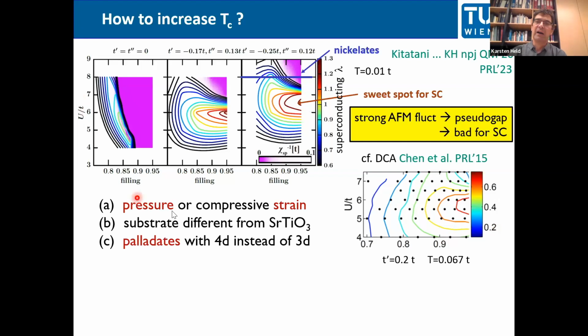And at the very beginning, we proposed 3 different ways to do so. Pressure, or you can also make strain within your plane. And the strain will increase the overlap of the wave functions because the sites are closer together, and that will increase T. You can also use a different substrate, or you can go to wave functions that are more extended, like 4D palladates instead of nickelates with 3D.